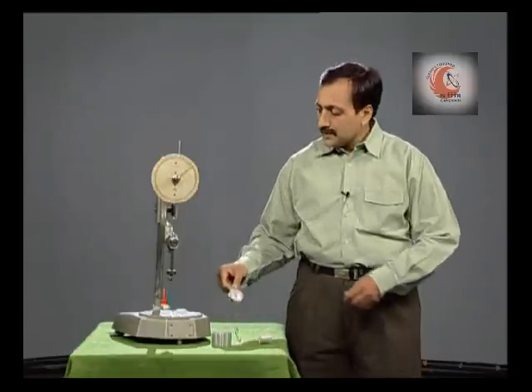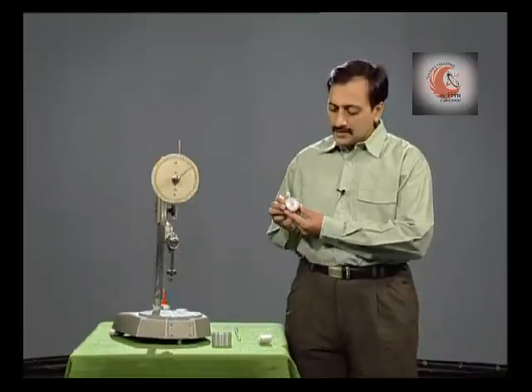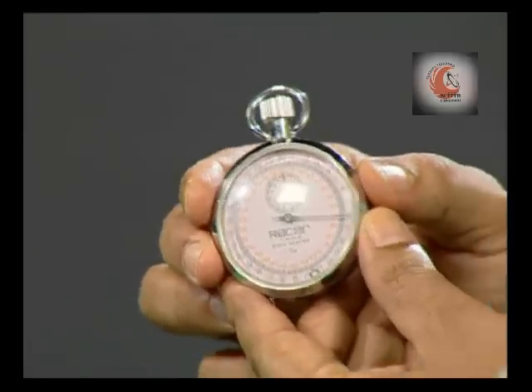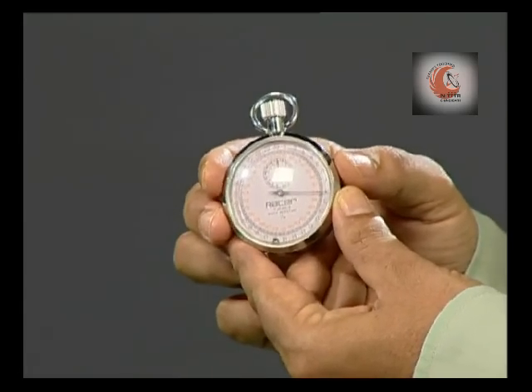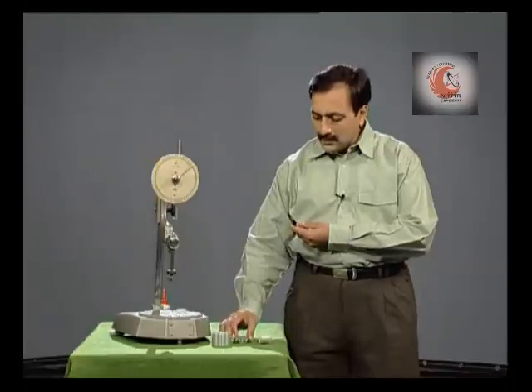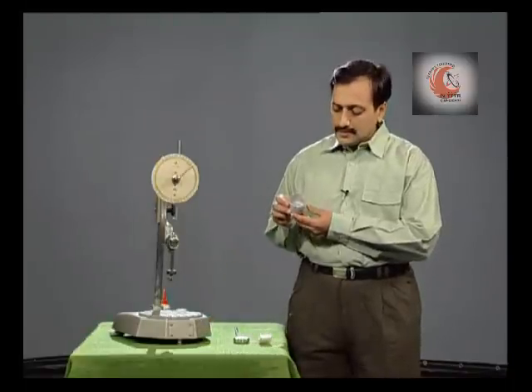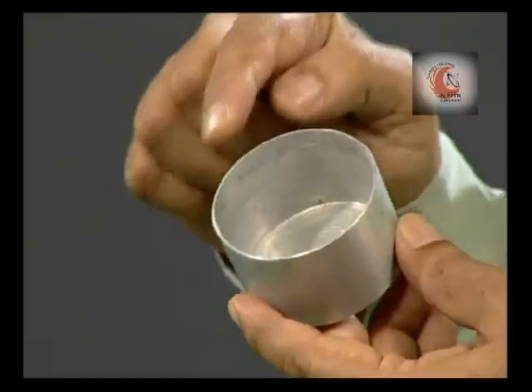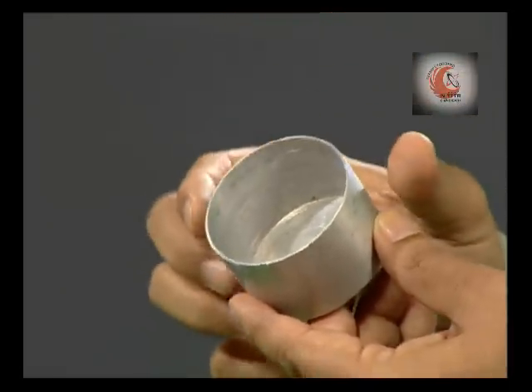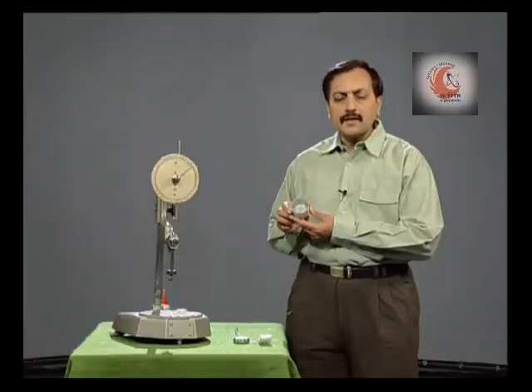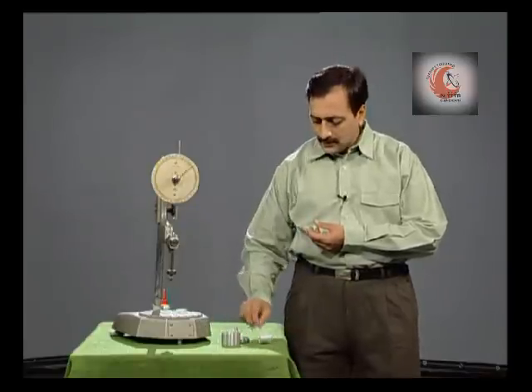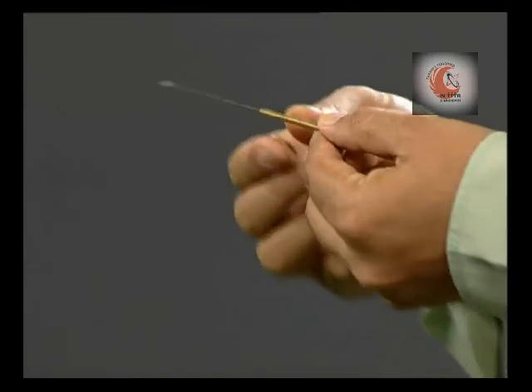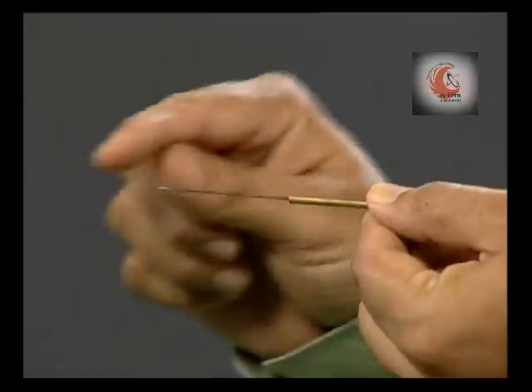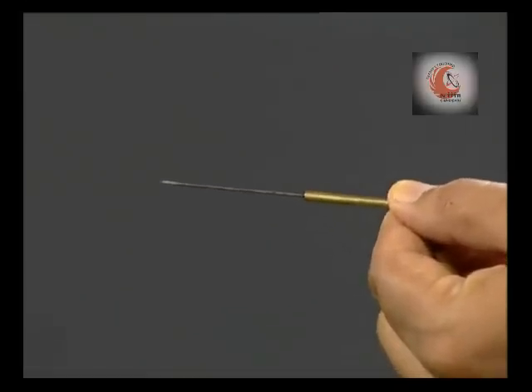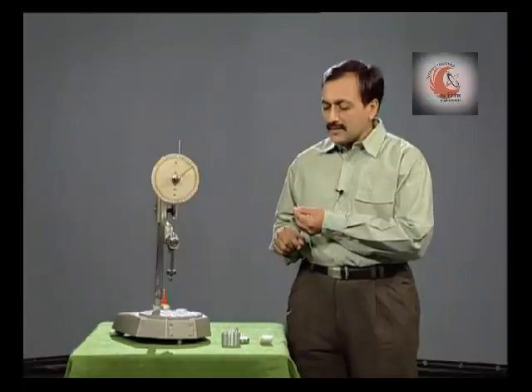If you are using a manual model, then we need a stopwatch which is accurate to measure up to 1/10 of a second. We also need a container to place the specimen. The diameter of the container is 55 mm and the depth is 35 mm. A steel or aluminium container is suitable for this purpose. The penetration needle is a straight edged and highly polished needle made of hard steel. The dimensions are as shown.